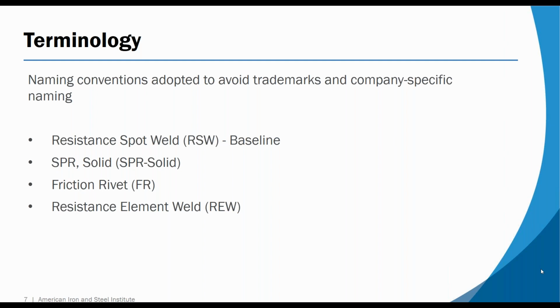And then finally, we studied resistance element welds. This is again a steel joining element that is punched through the aluminum sheet, mechanically clinched or fastened into place by interlocking, and then is resistance welded to the underlying steel sheets by either a resistance spot weld or projection weld, depending on the geometry of the particular element.